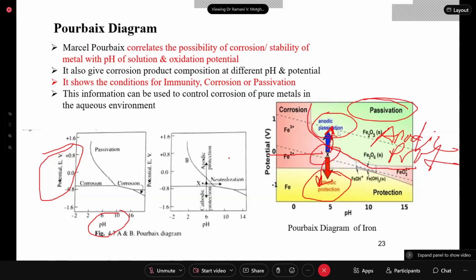Such a Pourbaix diagram, now this is the iron system, can be there only for these active passive behavior showing metals like nickel, titanium, aluminum, iron, chromium. If your potential, like this X point, is made anodic, it goes into anodic protection, that is, it forms a protective layer on the surface of the metal so that the underneath layers are protected. Or you change the pH. Suppose the pH here is 5, or in this diagram it is 6. If you change the pH, you are moving from the corrosion zone. This is the corrosion zone. This small part is also a corrosion zone. So you are moving from a corrosion zone to neutralization, that is pH 7 or 8. But that also to some extent only you can change the pH.